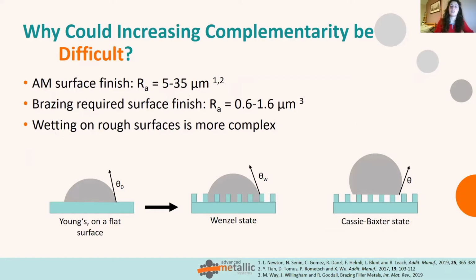It also turns out that wetting on rough surfaces is much more complex than the traditional Young's wetting that I explained earlier. It ends up being either the Wenzel state, where it fills the grooves on the surface, and this would be wetting, or the Cassie-Baxter state, where there are small air pockets trapped underneath the alloy, between the alloy and the surface, and this is typically associated with non-wetting states. A lot of the literature focuses on inducing this Cassie-Baxter state for hydrophobicity applications, such as self-cleaning windows and water repellent surfaces, but we need the opposite for brazing.